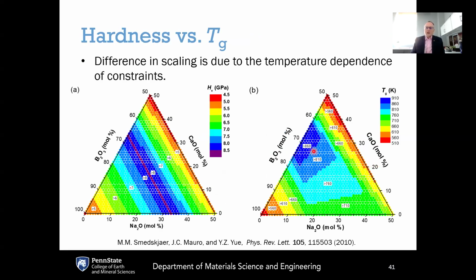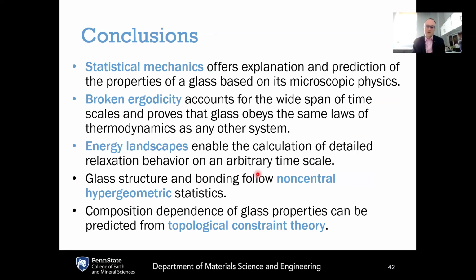This approach through temperature-dependent constraints provides a natural explanation for why properties vary differently, like why hardness scales differently than glass transition temperature. Even though they both depend on the connectivity of the network, hardness depends on the connectivity of the network at room temperature, and glass transition temperature depends on the number of constraints in the network at elevated temperatures in the glass transition region. And that's why these properties scale differently, even though they both go back to the number of constraints. So that does it for this lecture.